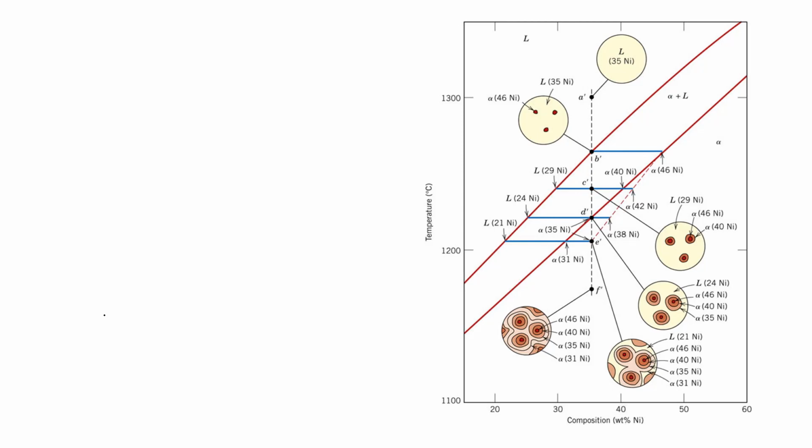That's very important. What it means is, for casting in the metals world, often it's not a very uniform composition. The first solid that forms has a different composition than the last solid that solidifies. And that's shown in this picture on the right here. So you can see the cores of these grains are different than the outside.